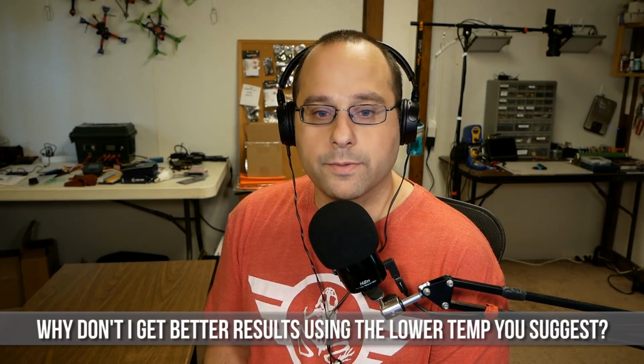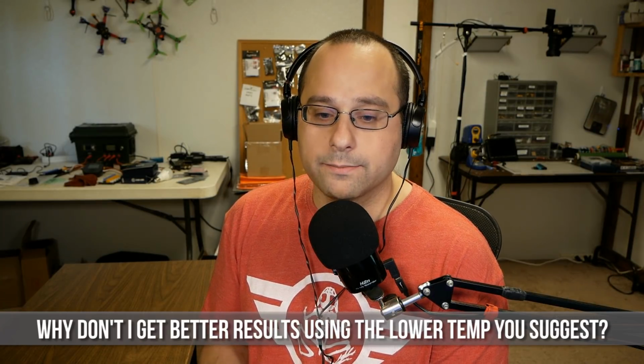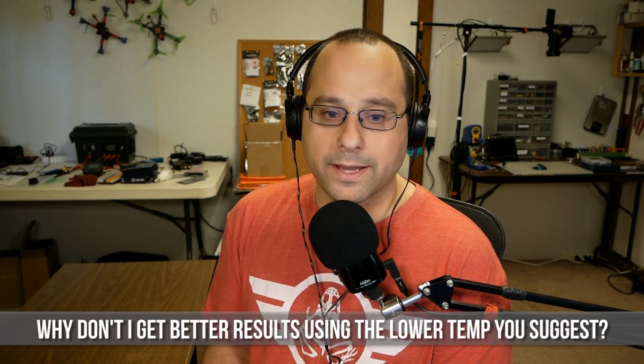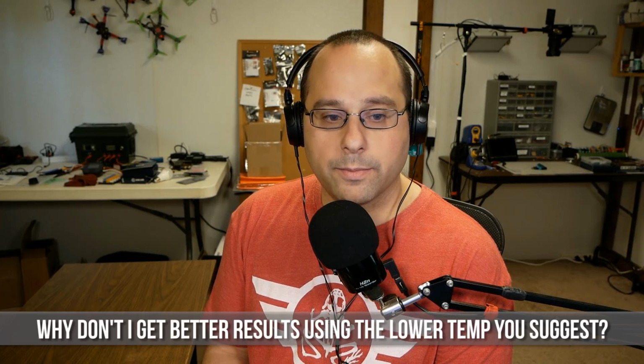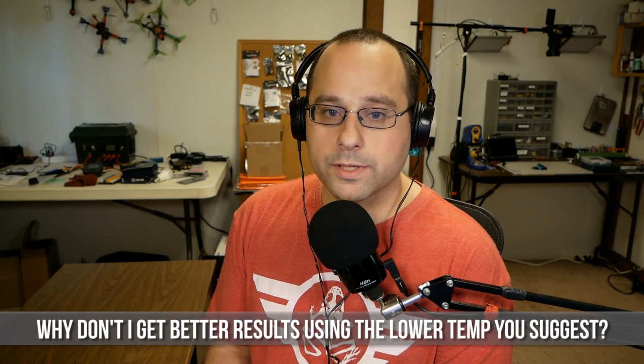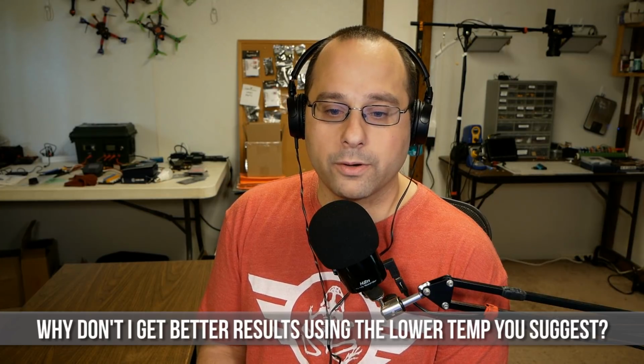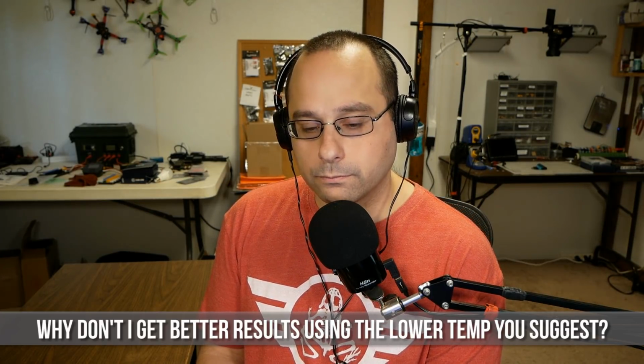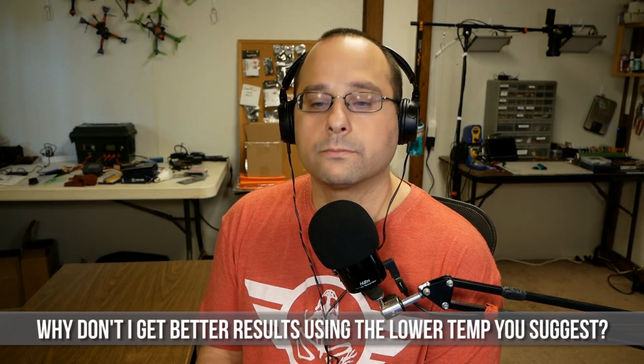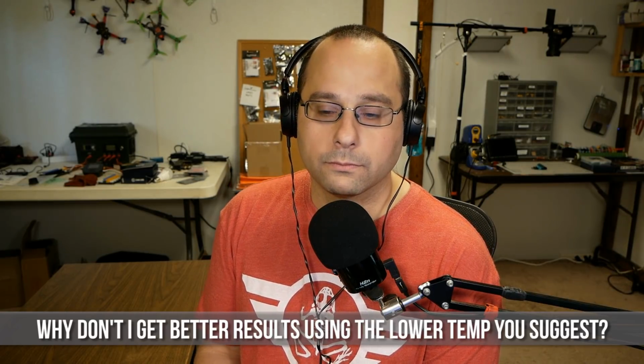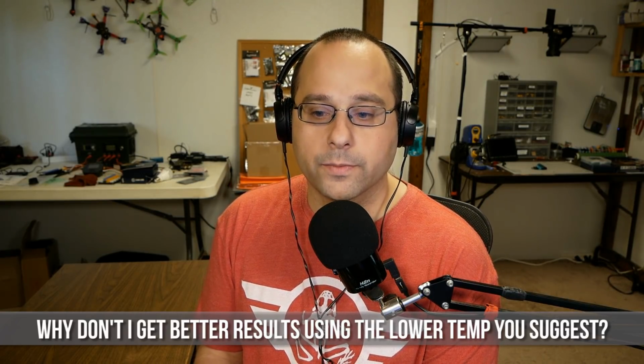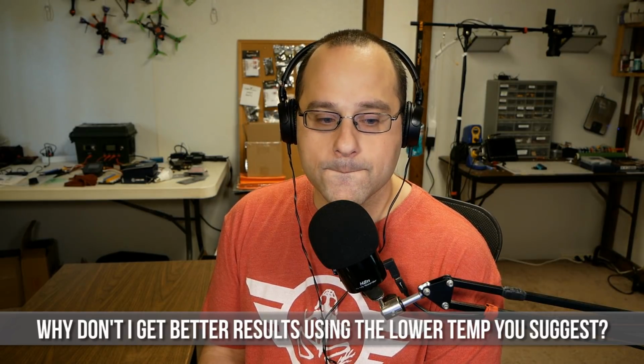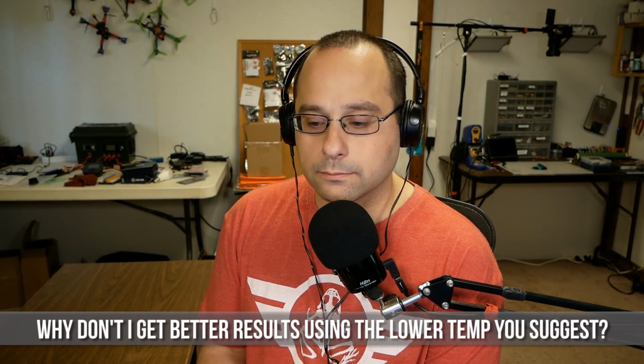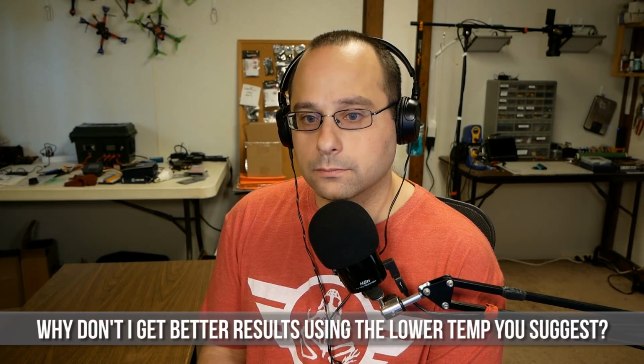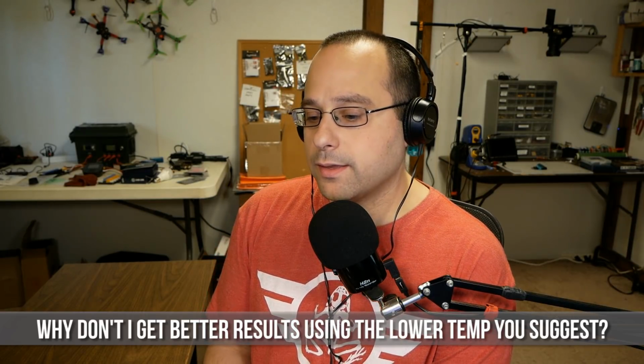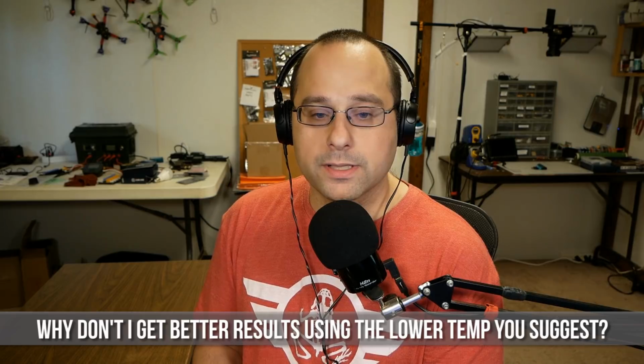As opposed to doing something like, well, certainly SMD, although not many people are doing surface mount by hand, though it can be done. But like doing through-hole chips onto a board, or through-hole components like that. Correct. You could use a much lower temperature than for wires, because you've got a small pad and a small leg on the IC. I see. So it doesn't draw away too much heat. So that's what you were seeing: the wire was pulling the heat away and it was taking longer to solder.